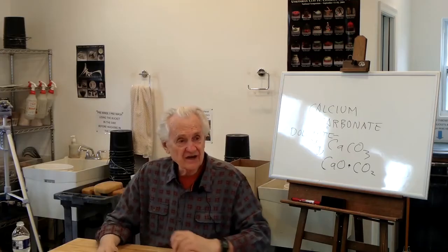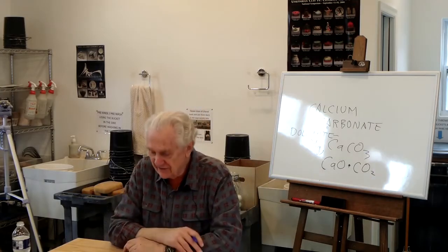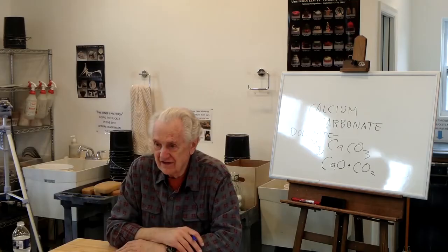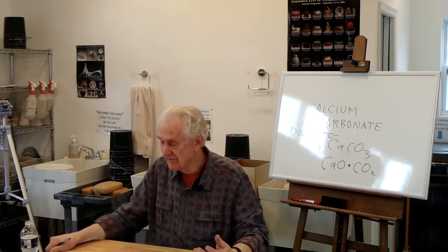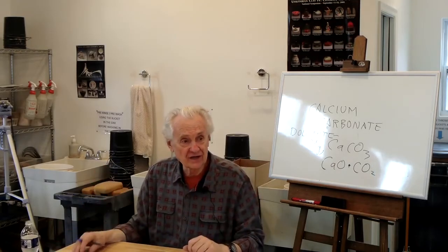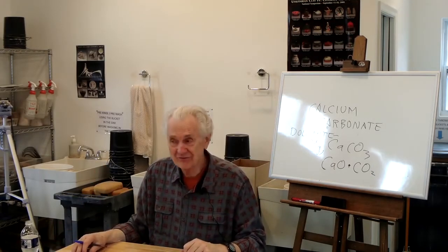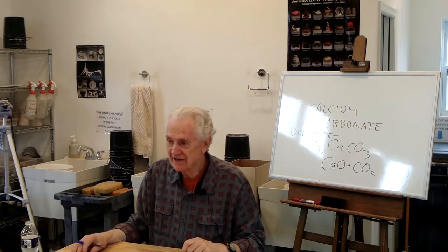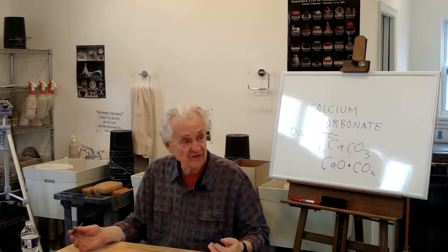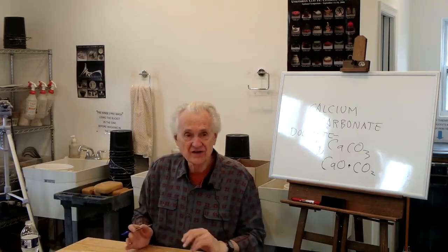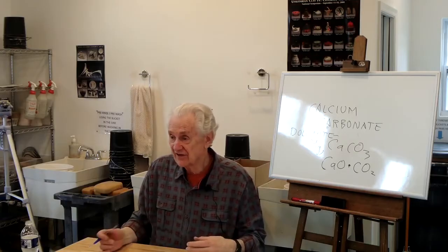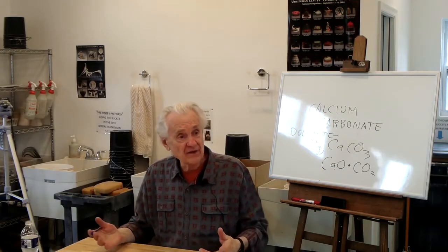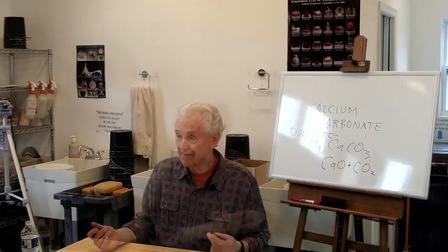And again, we're lucky because other forms of magnesium or magnesium oxide are really expensive. They're hard to chemically process, and here we've got this dolomite, which is really cheap. By the way, if you ever buy, quote, lime to put on your lawn, it's dolomite. So it's really cheap and really readily available. So here's a case where we're really lucky. This sometimes difficult to obtain element, magnesium oxide, is readily available. So that's one of the reasons why we can easily make satin glazes or satin matte glazes. The next one is a mineral called wollastonite.